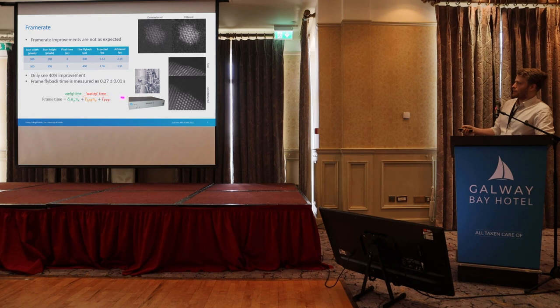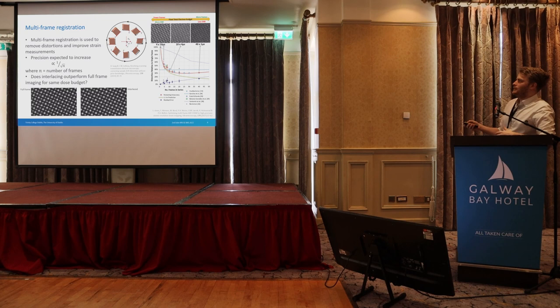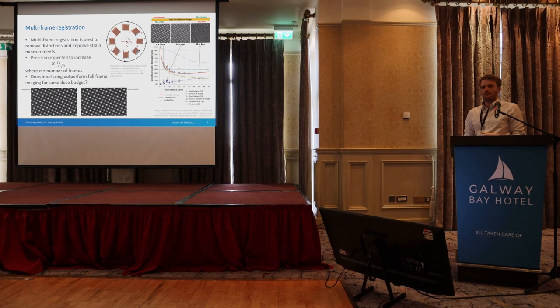To go further you'd need to address the hardware. Another thing we've been doing — which is quite popular — is that the scanning distortions are a bit unfortunate but inevitable. One way to handle this is multi-frame imaging, where we use a stack of images to diagnose and correct any drift and vibrations. Ideally we want some rotation between the images, as it helps diagnose distortions. Brown's 2017 paper showed a strain precision approach that works quite well. For ferroelectric materials, semiconductors, catalysis and similar applications, there's a lot of interest in strain engineering.